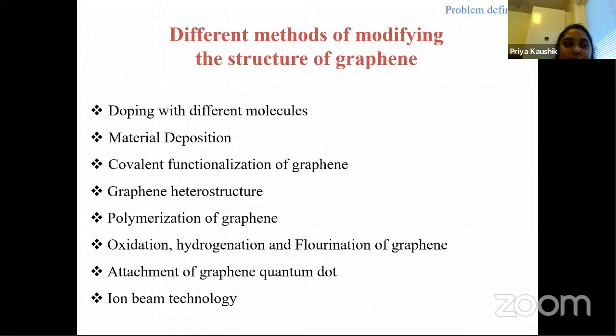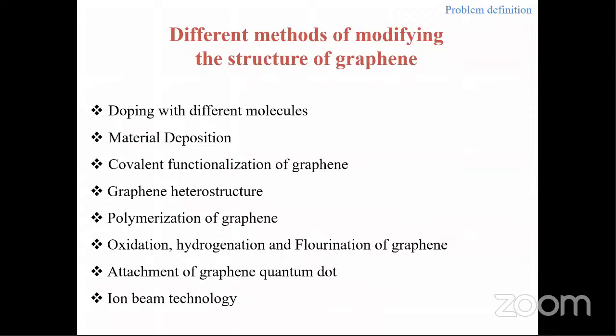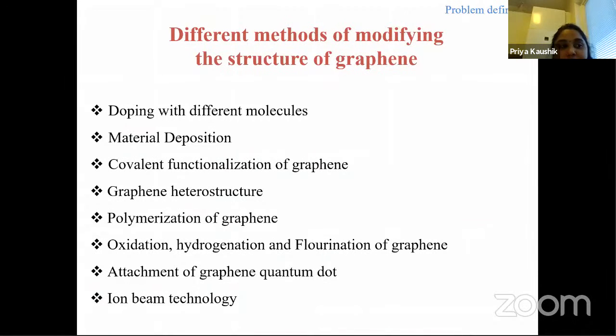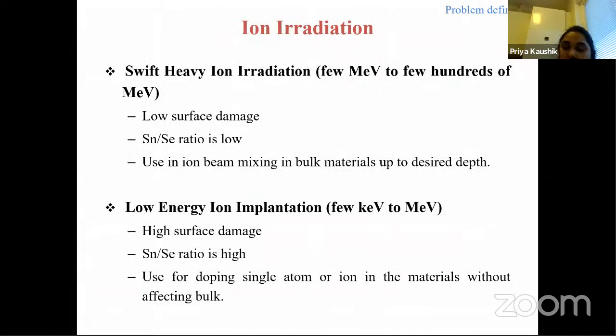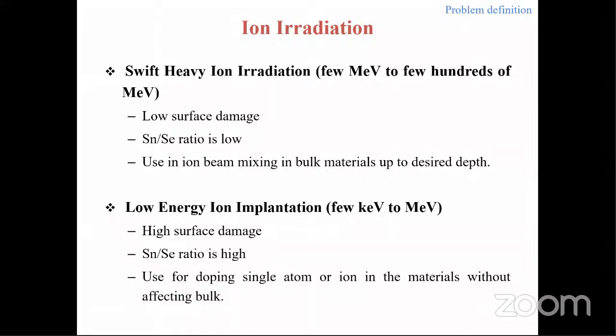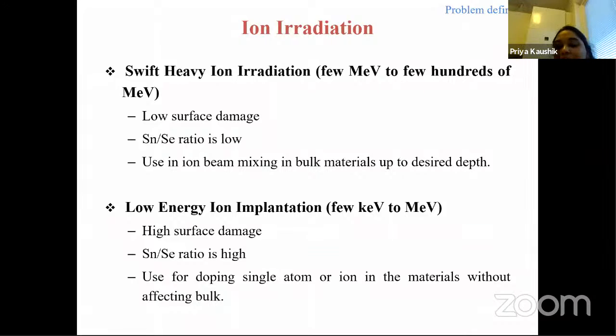The topic which I am going to discuss today is ion beam technology. In ion beam technology, we use ion beams to introduce structural modification in graphene. It can be done by two methods: swift heavy ion irradiation and low energy ion implantation. Swift heavy ion irradiation is a process in which high energy radiation is used, with energy from mega electron volt to a few hundred MeV, and in low energy ion implantation, lower energy is used, from keV to MeV.